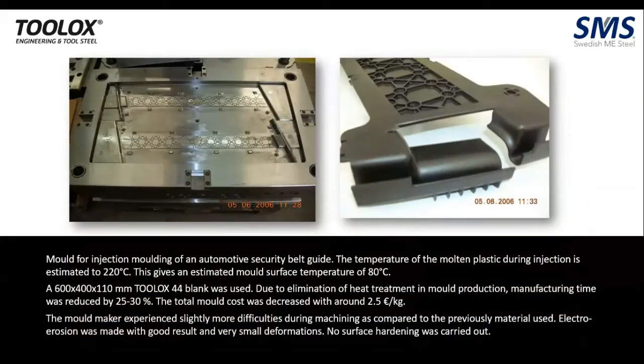So this is injection molding for an automotive security belt guide. The temperature of the molten plastic during injection is 220 degrees centigrade. This gives an estimated mold surface temperature of 80 degrees centigrade. The blank used was 600 by 400 by 110 mm. There was no heat treatment. Manufacturing time was reduced by 25 to 30 percent. So that's the thing here.